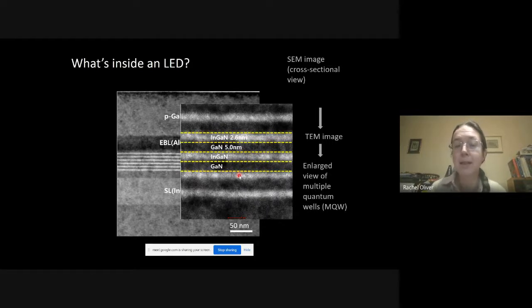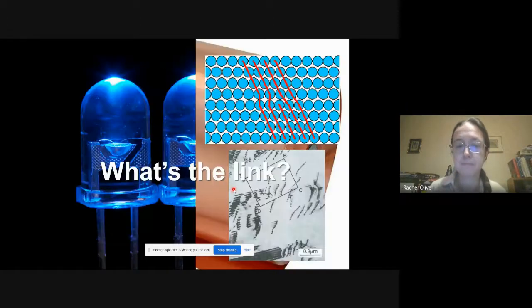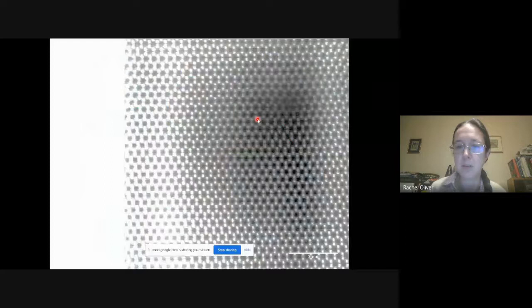So this is the real light emitting part of the light emitting diode, consisting in this commercial LED that we've sectioned here of layers of indium gallium nitride, about 2 to 3 nanometers thick, separated by slightly thicker layers of gallium nitride. And that's where this talk is going to focus, on these quantum wells and their structure and properties, their materials science. So what is the link between the copper with the dislocations controlling its mechanical properties, which I mentioned at the beginning, and these light-emitting diodes? Well, the link is in these defects, these dislocations that I mentioned.